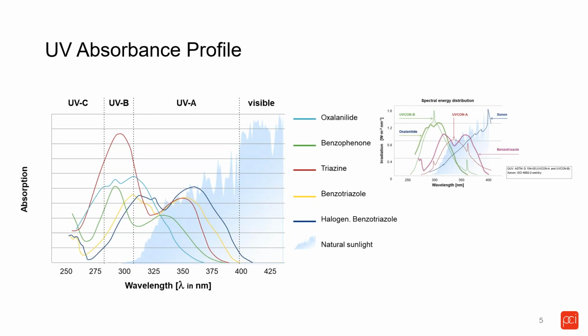As you can see in the small graph on the right side, usually we can either do xenon weatherometer testing for Xenon weathering, we can do QUV with UVA lamps, which is shown here as UVA-340, or we can do QUVB. They're very different, as you can see by the intensity and by the wavelength of those lamps. But what we can say from this graph is that xenon will probably be the one that correlates the most to outdoor weathering, because as we can see, the spectrum of the xenon lamps goes in the same direction as the natural sunlight, starting very low at 300 nanometers and increasing just like the natural sunlight when we go to the visible light. So xenon will probably be one of the best accelerated weathering tests.